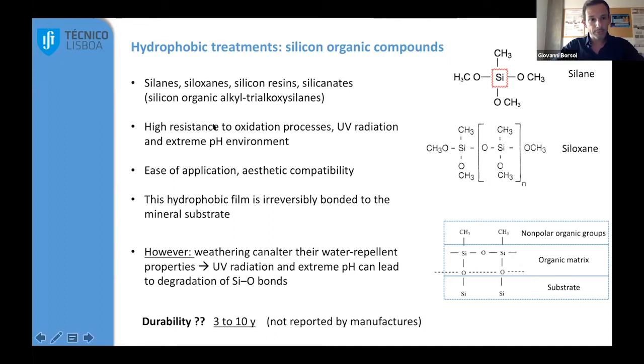So basically those materials, some like silane, siloxane, and other resins, are based on silica and functionalized with the alkylic group. And those usually have a lot of benefits if used as a hydrophobic product, because usually you have a high resistance to oxidation processes, especially in brand new paints or products, and extreme pH environment resistance. But on the other side, we know that there might be problems related exactly to those two components, especially after a few years.